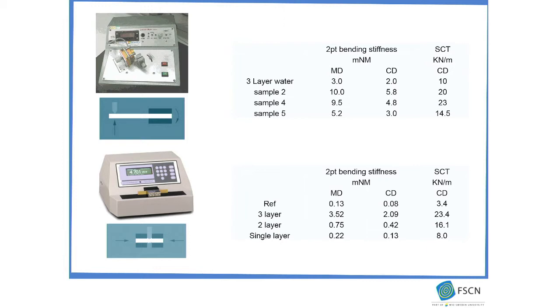And this is the material produced from the solution infusion process. As you can see, the number is not that impressive. It's because even though we have the vacuum to trap all the composites together, the adhesive process is not that good, so the paper is not really sticking to each other. During the bending stiffness test, the inner shear will delaminate the materials. So we have to work on how we can achieve such a uniform material.